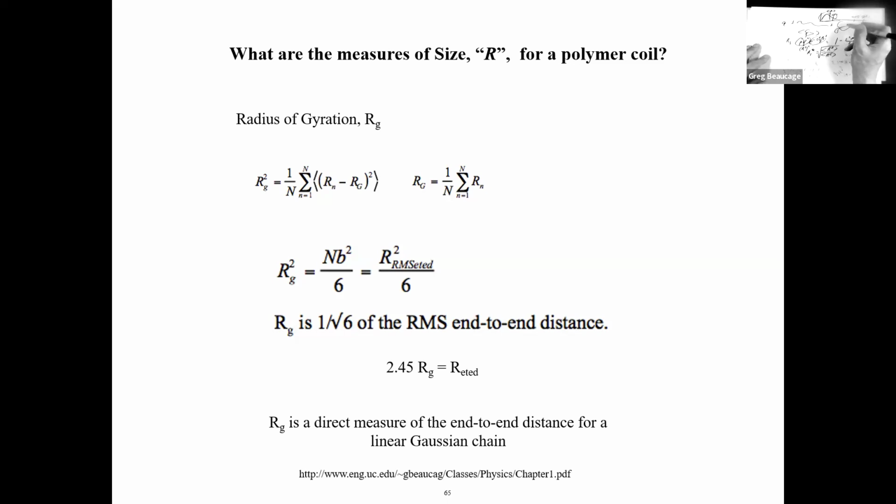That said, if you have a monodisperse system, with number versus R, you just have one value, then all these moments are equal. You have the average of R equals the average of R squared equals the average of R6 equals the average of R8. And so if you have monodisperse, RG is a perfectly valid thing to use. But if you have polydisperse, it gets pretty goofy, it's going to be way too large of a number.